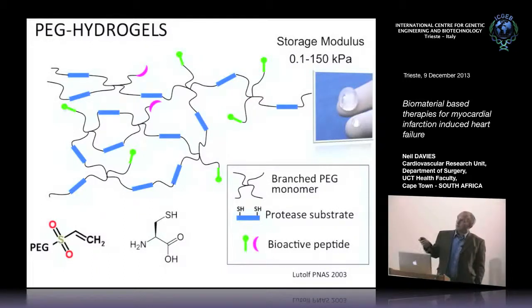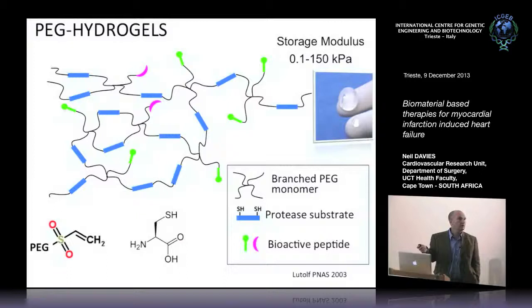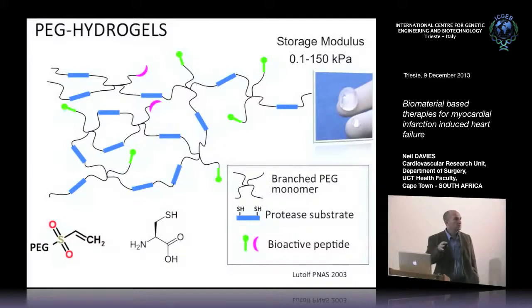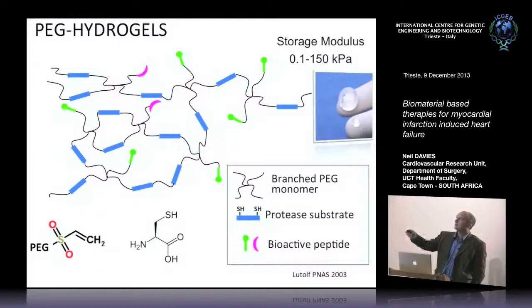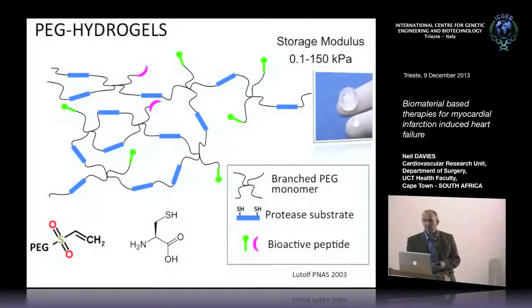If you take a peptide and put a cysteine at either end, you have thiols at either end, forming a bifunctional cross-linker. If you get the ratios correct, you can cross-link everything into essentially one gigantic molecule — that's what our hydrogels are. By using peptides, we can introduce enzymatic cleavage sites, meaning the gels will break down due to cellular invasion. You can also couple bioactive peptides, cell signaling peptides, and cell binding peptides.